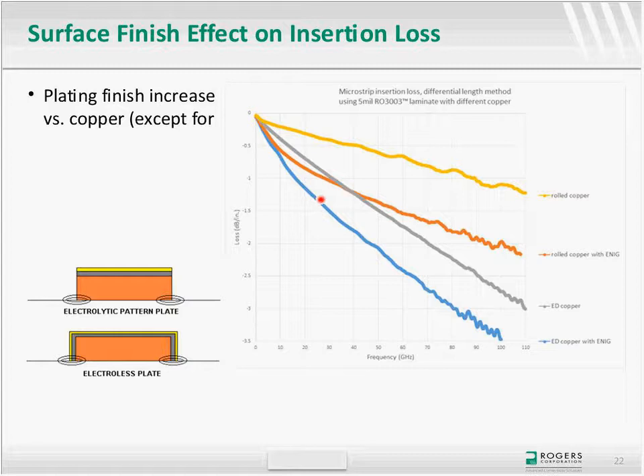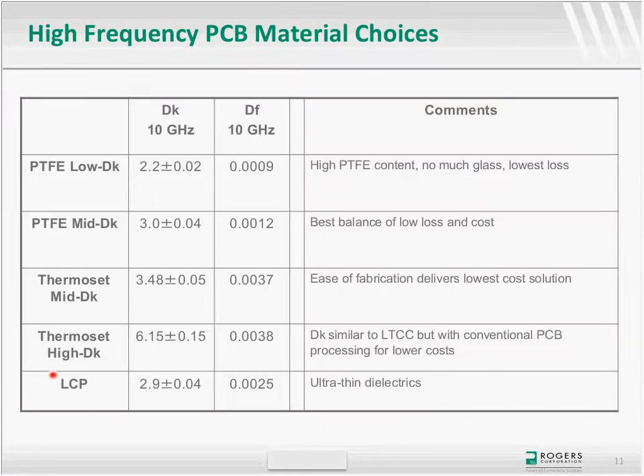For LCP material, how is the stability with the temperature and the shrinkage in thickness when it's laminated? The LCP material, the one thing to take into consideration is that it's an unsupported material, so it's not so much the shrinkage, but it's because of the extreme flexibility of this product. So we found that the facilities that process LCP, if these are facilities that have experience in working with flex circuit materials, polyimide materials, for example, they tend to be able to have a better approach on how to manage this so that they don't stretch materials in the handling, because they're used to doing that. The circuit board facilities that tend to process more rigid, it may be something that they have to learn to adapt, but it's not something that can't be done.